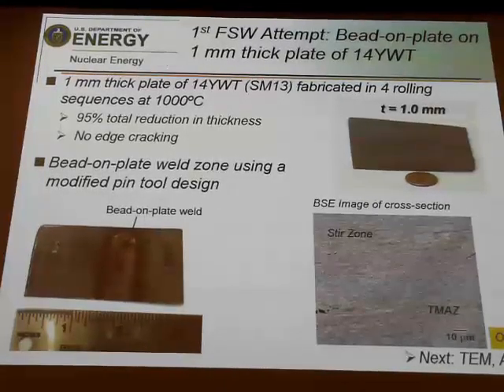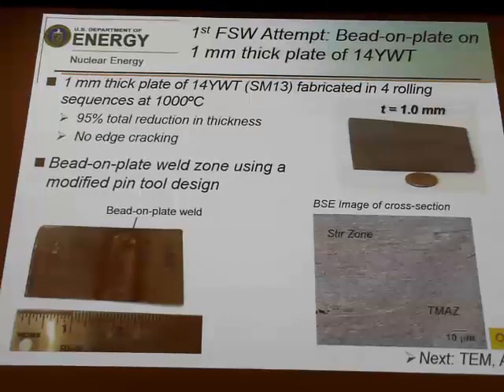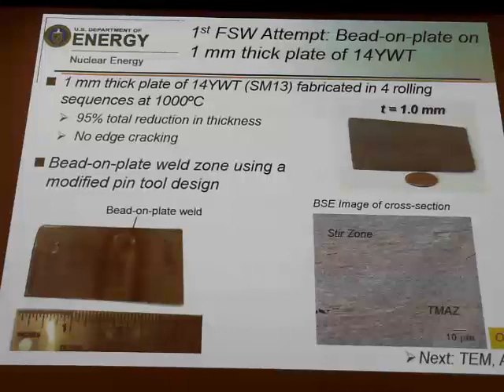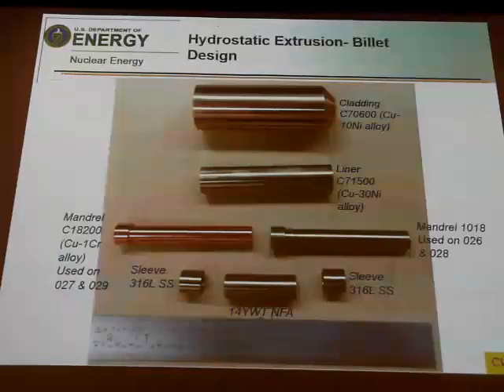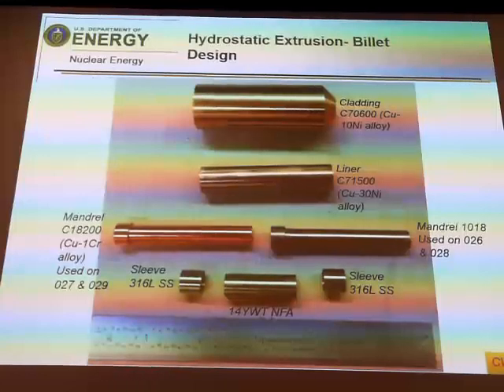And this is a bead-on-plate weld that was actually done, a friction stir weld going across a plate to weld 2 1 millimeter thick plates together. That went fairly well, actually. You can just see here the stir zone versus the heat affected zone off to the right. You don't really see much difference at all. We're doing a tensile test on this material. I won't show it, but that data looks quite good as well. So we're making some progress in learning how to weld that material.